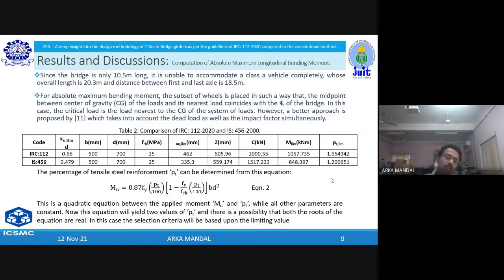However, a better approach is proposed by paper number 11, which is given in the last slide in the references part, which takes into account the dead load as well as the impact factor simultaneously. Now computing all the moments and shear forces, what we can see from table 2 is that for a definite section, 500 mm by 700 mm, and same grade of concrete and steel, IRC 112 gives a better moment of resistance and has a greater value of limiting percentage of steel. So with this, we can see that using IRC 112 over IS 456 would be a better and more efficient approach.